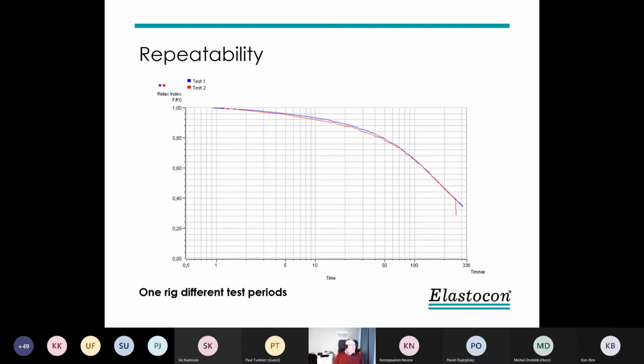If you look at the accuracy of the system, the idea with the continuous system is to avoid touching the sample, moving the samples, handling the samples during the aging, because all that introduces errors. And here is a very early test where we tested the same material in one rig at different test periods, and they correspond quite well.